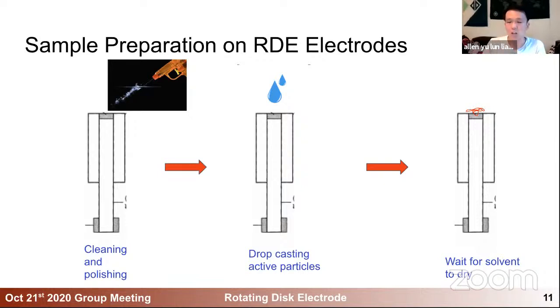However, if you want to drop cast any active material on it so you can study the active material itself rather than the disc electrode material, of course, you can do that. Just drop cast active material particles on top of it. One interesting thing is that the shroud surrounding the active electrode disk is plastic and often nonpolar, and the metal in the middle can be somewhat more polar. So if you drop cast a more polar solvent such as water or ethanol, the surface tension of the liquid will pretty much keep whatever you drop cast on the electrode within the disk area. So it's quite niche, quite cool.